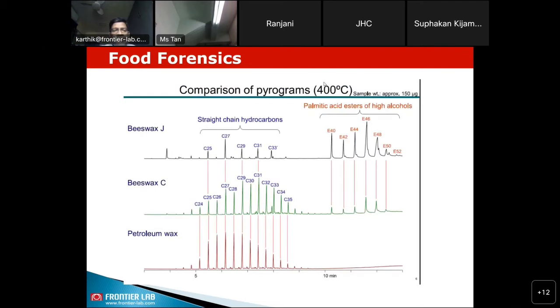So we can analyze this beeswax, coming from two different sources, and we also have analyzed the petroleum wax. So what you can see is, the peaks of straight chain hydrocarbons may be found in beeswax as well as in petroleum wax. So if you are characterizing using only these short straight chain hydrocarbons, then you won't be able to differentiate, because even when people bring petroleum wax mixed with beeswax for product gain, you may not be able to identify or determine this difference. But when you see the other data like palmitic acid esters of high alcohols, this is something you don't find in petroleum wax. So this is how you can see the product differentiation and also the blend of petroleum wax in the beeswax.